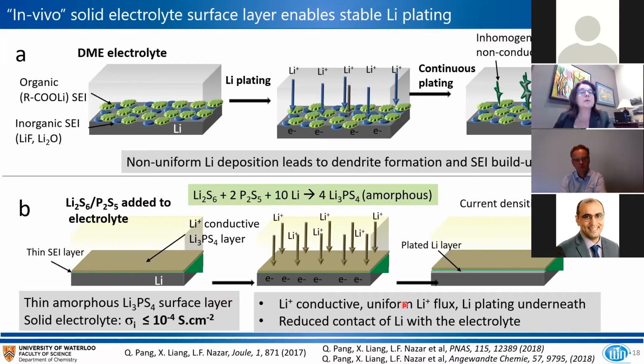And so we are able to obtain uniform lithium flux. We again plate lithium underneath the layer. This is all shown in these papers that are cited below. And most importantly, we reduce contact of lithium with the electrolyte because the lithium is plated underneath this film. Whereas in the case of just a simple dimethoxyethane electrolyte, we see a lot of dendritic growth and basically non-homogeneous deposition.